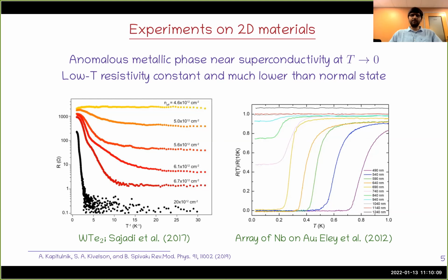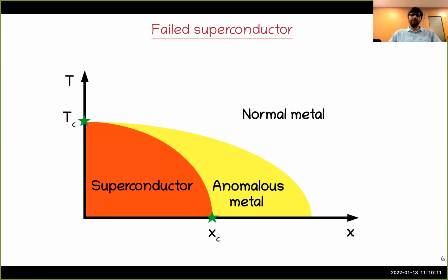So essentially, the picture that we have, or what we expect for these two-dimensional disordered superconducting materials, is that you have some superconducting phase, and it can have this thermal phase transition where above Tc it's a normal metal. But now if you tune some non-thermal parameter, let's say like a gate voltage or interactions or magnetic field, you seem to go to some anomalous metal phase before you go into a normal metal. And this phase is what I call a failed superconductor.